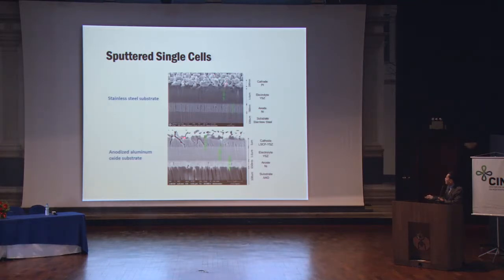But here we also have the cell deposited on a porous substrate. We use anodized aluminum oxide, or AAO, because it has a very well-defined porous structure, and we show the porous nickel anode, the YSZ electrolyte, and the LSCF cathode.